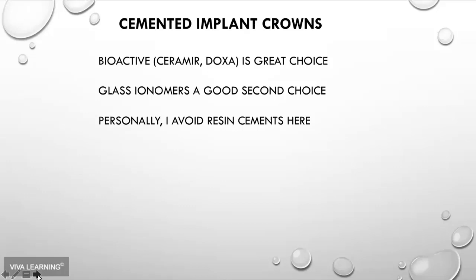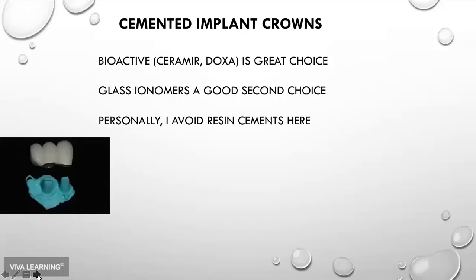When I do have to cement an implant crown, I try to stay away from the resins because a lot of this research is pointing back to resin cements causing the peri-implantitis. So I try to stay away from resin cements. The Ceramir cement is a non-resin cement, has good retention properties. So that to me has been my first choice. Glass ionomers I've used for a long time with good success, but it's just this is the one place where I really stay away from resin cements. If you are going to use a cement, a quick and easy technique I saw Bob Margis present years ago.